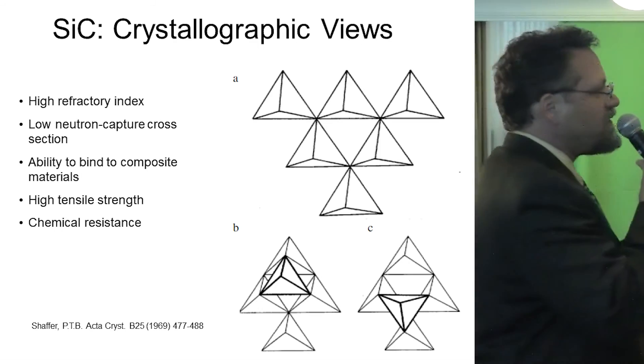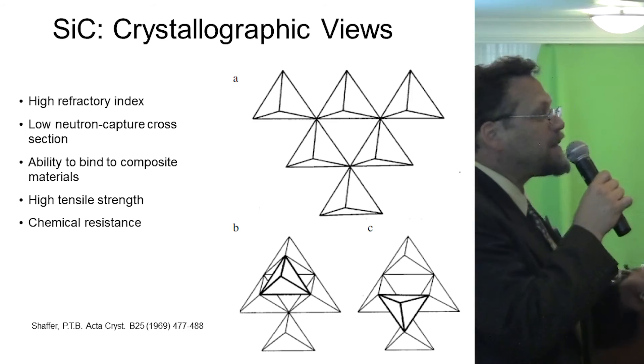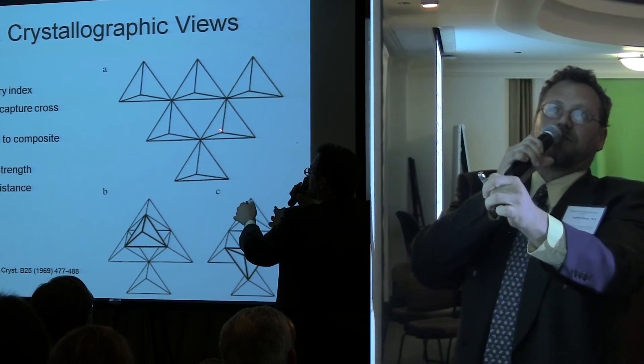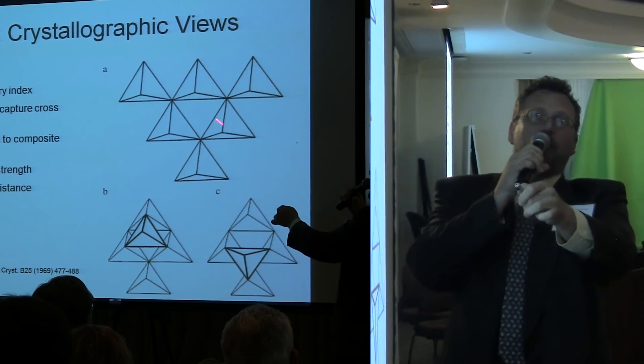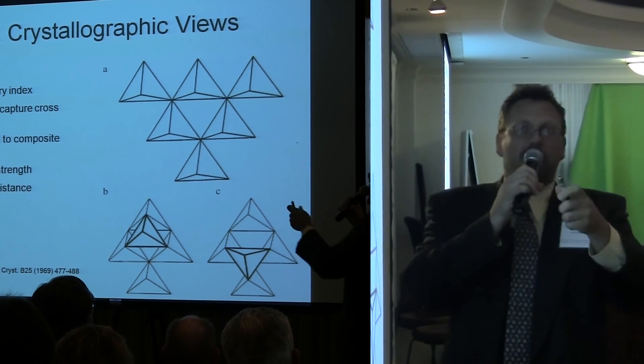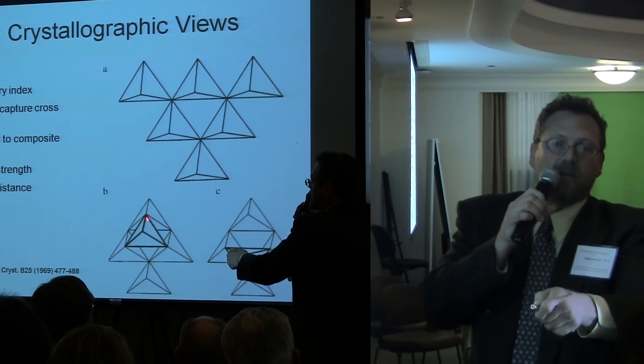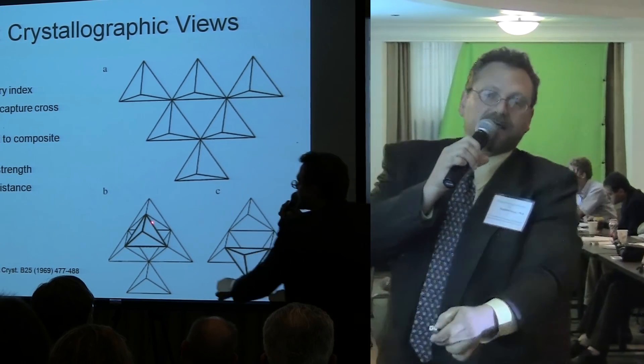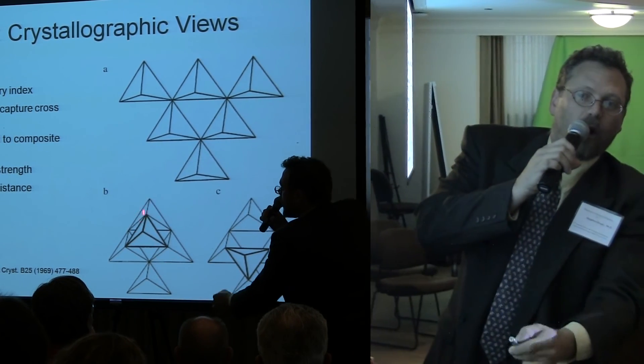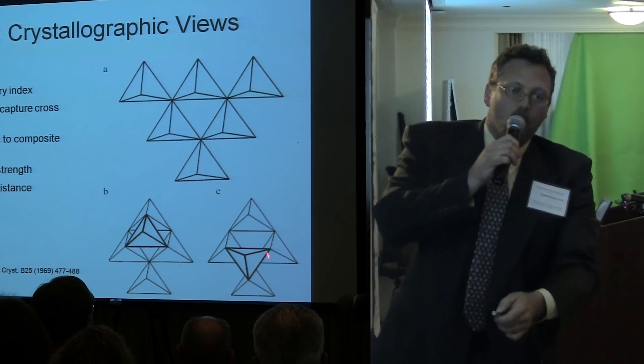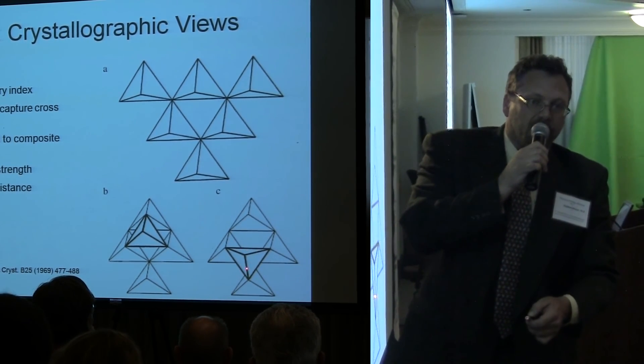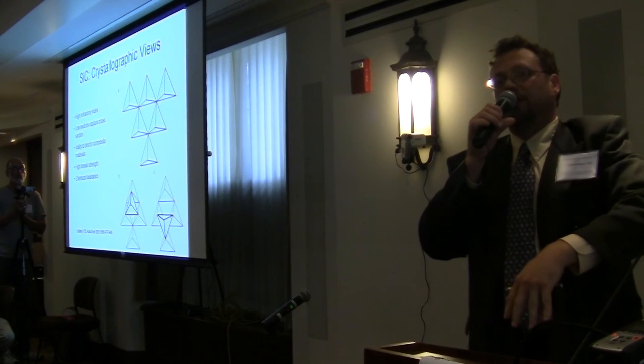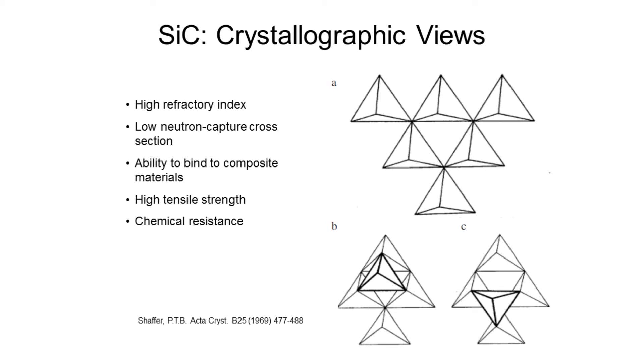Silicon carbide is a very interesting material with fabulous properties. These are represented in this cartoon as solid objects. We've got silicon at the vertices and carbon at the center — this is an opaque tetrahedron. There are several ways we can stack these tetrahedra on top of one another: in a parallel fashion, so all the points are pointing in one direction, or in an anti-parallel fashion. When stacked anti-parallel, look at what happens — there's a hole here, representing a drop in symmetry and concomitantly an increase in chemical reactivity potential.